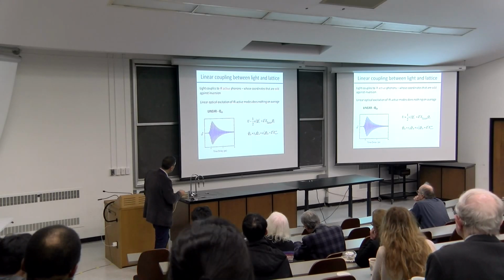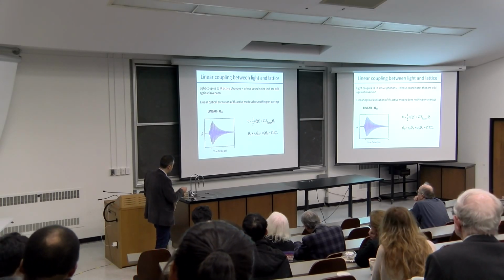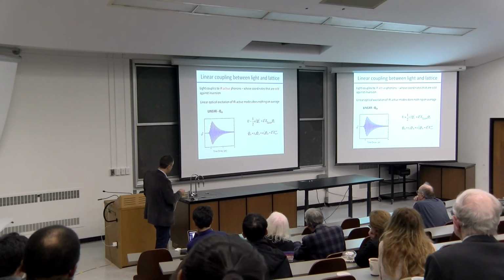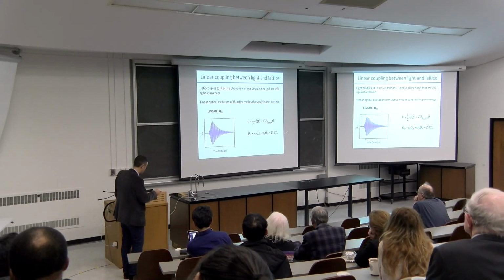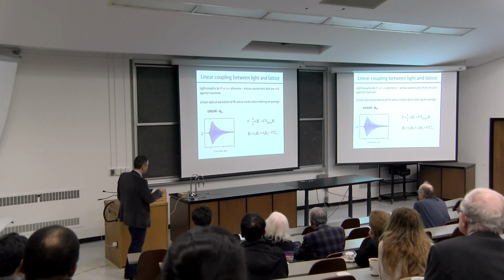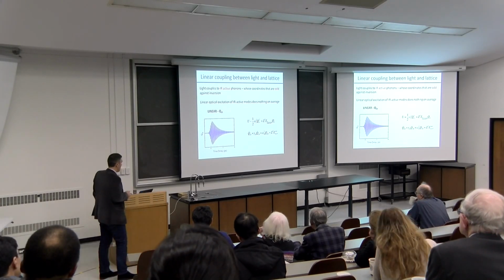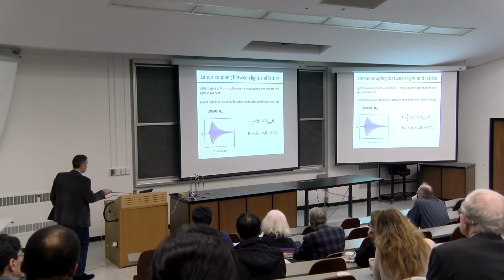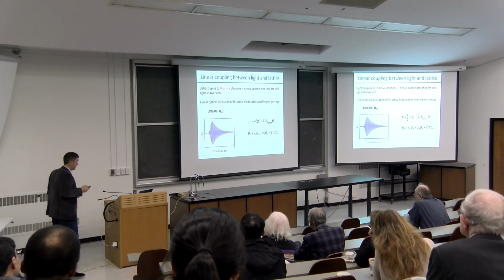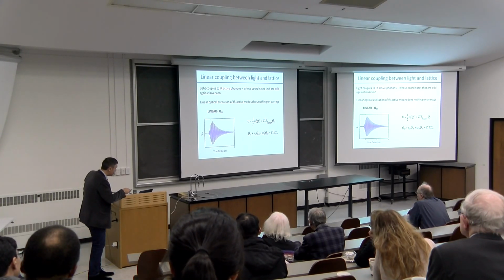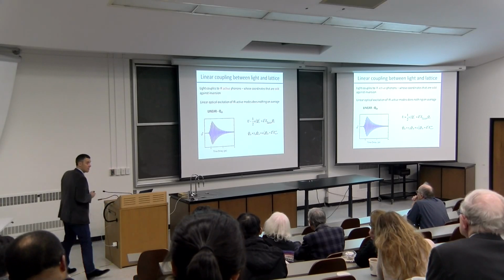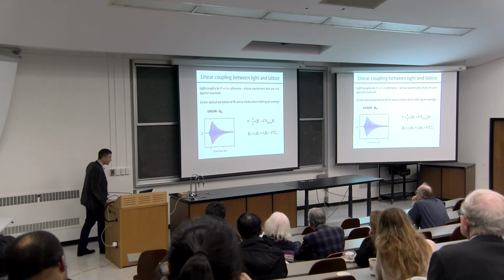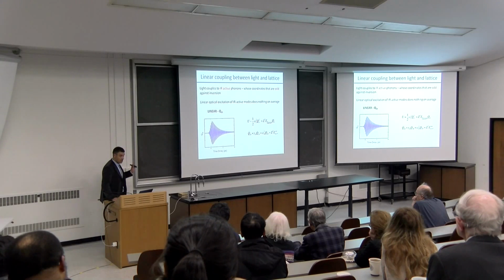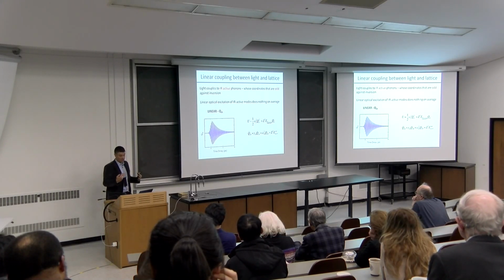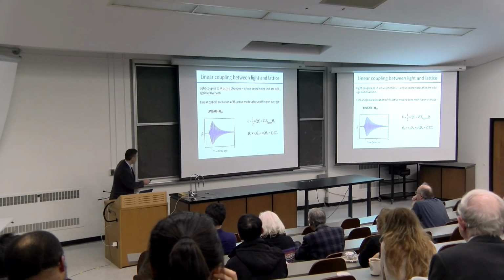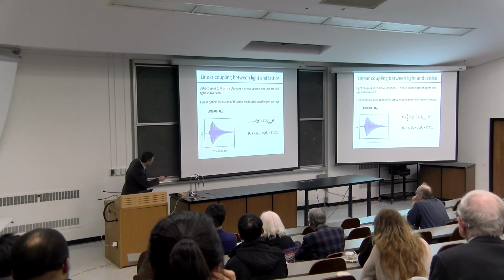And then there's a term in the energy that is proportional to, again, the bond charge, which is this quantity, the laser field, and the coordinate itself. So this boils down to a damped harmonic oscillator that is driven by the laser field, with a prefactor that tells me how polarizable the medium is. The Z star is basically the oscillator strength of this. So once we know this, let's think in the same way that we do in nonlinear optics, what happens if the light field is very large? So this number here becomes very large.